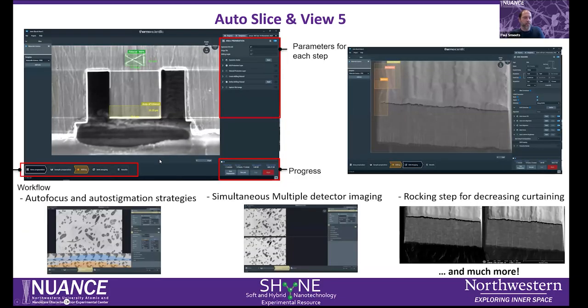This is a screenshot of that software. What we see here is an ion beam image. We're at a stage tilt of 52 degrees to be perpendicular to the ion beam. Down here in the software is a workflow, where you can have so-called area preparation, removing areas surrounding your material so that it's visible to the electron beam.